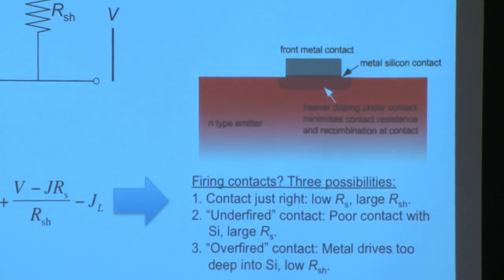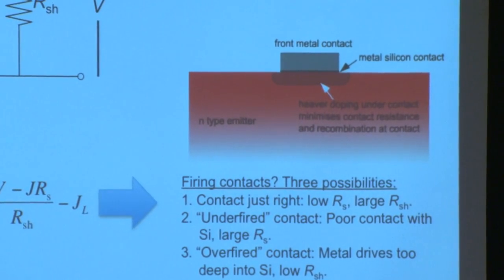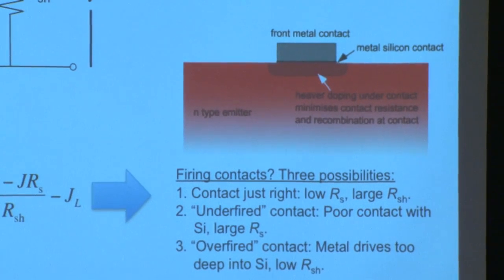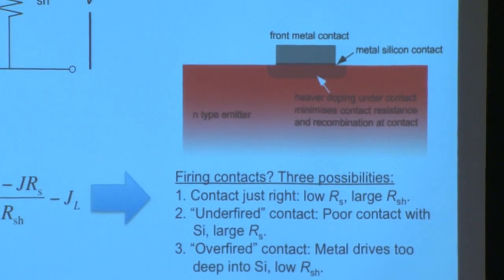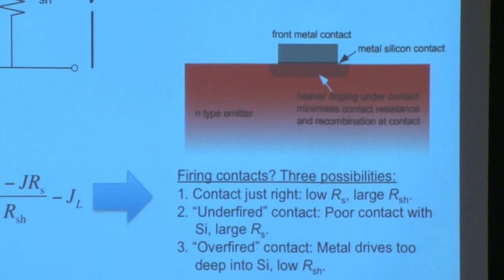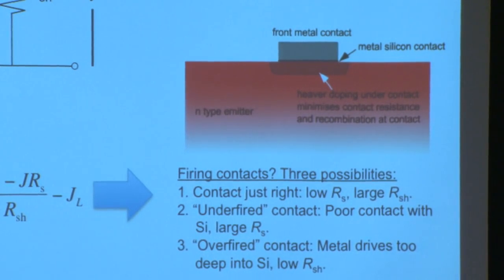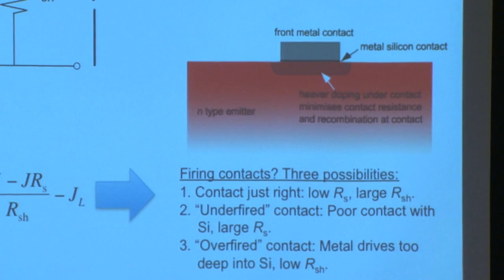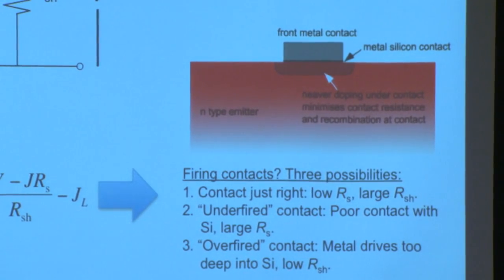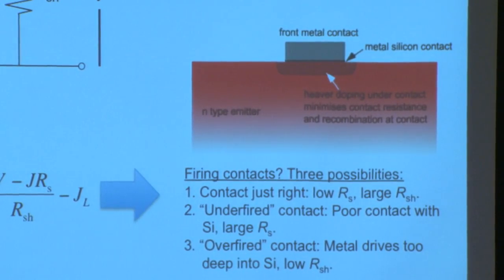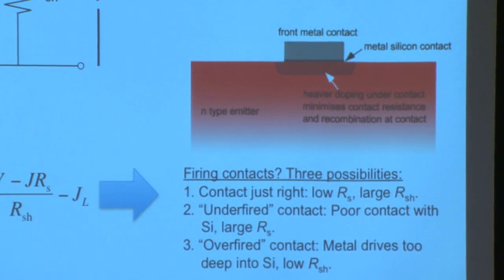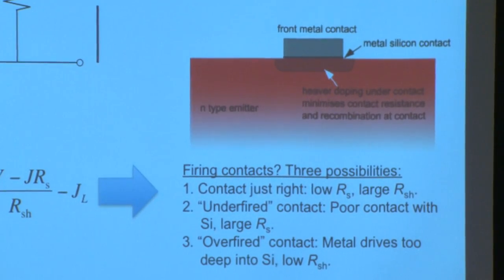Let's say you have nickel and silicon. You'd be looking for it to form a nickel silicide at that interface. Okay. And that's where you go to your phase diagrams and figure out what temperature those, say, intermetallics should form, and then you're targeting that particular temperature during your ramp. Okay. And of course, it's not only phase diagrams, which are under equilibrium conditions. Kinetics are involved as well, so it becomes a rather tricky process.